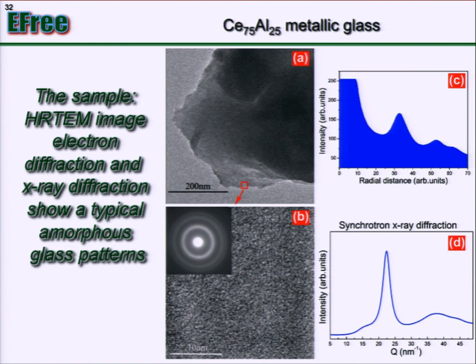So this was very puzzling, and this relates to a century-old question: does glass have long-range order? The definition of glass, if you look on the web, says it has no long-range order. But if it has no long-range order, how can you tell, if you have a long ribbon, that this point and this point have the same orientation once it crystallizes? One thinking is that maybe the crystal grows from one point to the other, but we cut two pieces of this ribbon and ended up with the same crystal orientation, and so they cannot see each other.